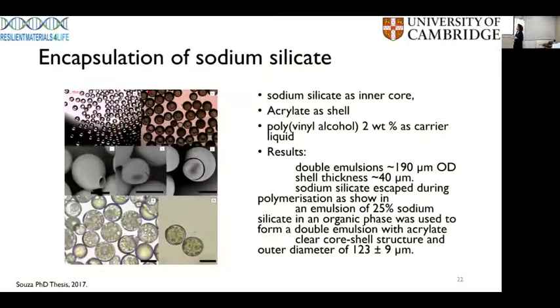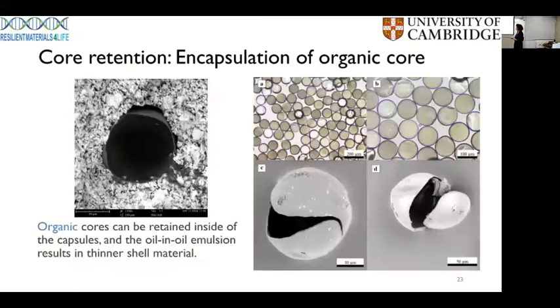To cope with that, there are some alternatives, but basically we need to play with density. One alternative is to dissolve that sodium silicate in an organic phase, because then you adjust the density of the system, and then you can produce the capsules. But again, they are emulsion-like in shape. Organic cores are a lot easier to encapsulate when we are thinking about techniques for producing microcapsules in general. And because the molecules are a lot bigger, they are retained inside the shell a lot more easily as well. So those are classic examples of double emulsions and microcapsules produced with an organic core.